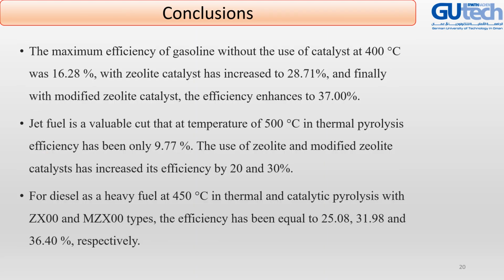So as a conclusion, we can say that the maximum efficiency of gasoline without the use of catalyst is at 400 degrees Celsius, and the amount is 16.28. With zeolite catalyst, it has increased to 28.71, and finally with modified zeolite catalyst, the efficiency of the gasoline production reaches 37%.